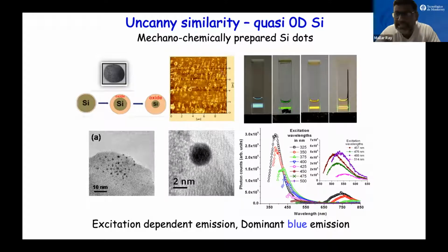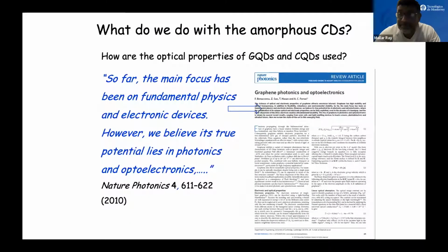Now, one very easy answer would be, okay, these dots are not playing the role, it's the surface species. But let me tell you that there have been many works. In fact, we have also spent almost 10 years trying to understand what exactly is the role of the surface species. But it is not emission only from the surface species, which I can assure from the experience that we have had. So it's not just the surface. Silicon and carbon dots are not just scaffolds of some chromophores which are on the surface. They also have a role to play. Surface definitely has a role to play in conjunction with what is there in the core. So this is still an active area of research, and I believe some of you might be interested in this field and in carrying it forward to some conclusive understanding of this emission mechanism.